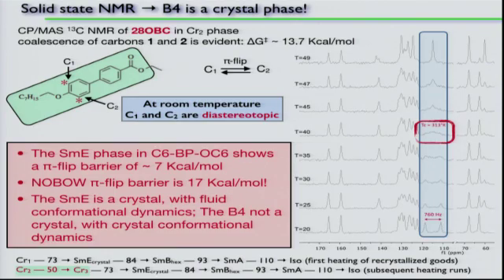so you can tell at room temperature that these 2 carbons are giving 2 peaks in this solid state carbon NMR spectrum. The fact that they're giving 2 peaks means that they can't be the same. They can't be homotopic. They can't be existing in identical environments. And if you freeze that rotation, you can see that one of these carbons is next to that carbon, and the other carbon is farther away from that carbon. They're different. They're heterotopic, or diastereotopic. So they should have by symmetry different chemical shifts in the NMR.